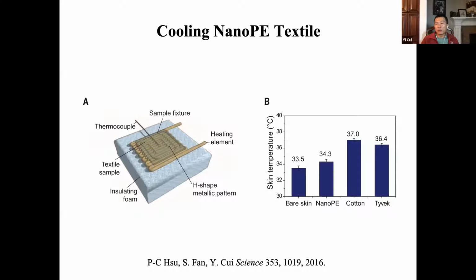But again, I think in Juntu's talk, Juntu was showing you already, if your ambient temperature goes up, because the environment also radiates towards you, this delta T between your skin and the environment is not big enough, and then your cooling power is actually reduced. So bear in mind, it's within a limited range of radiation cooling. It has to be below 29, 30 degrees Celsius. But with this understanding, the first demonstration in the Science paper is not a textile yet. It's non-woven, right? So we need to make it a textile.